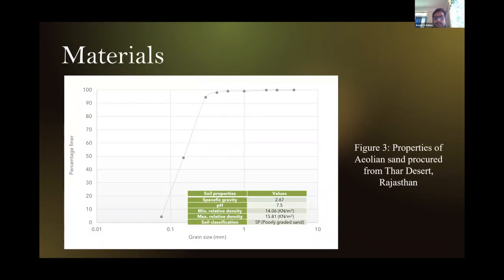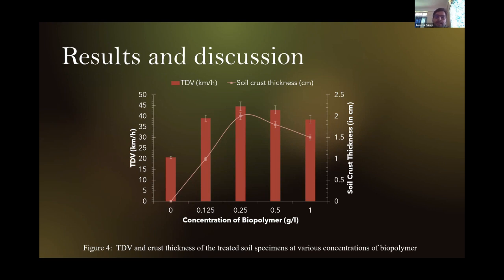So we collected the soil from Thar Desert, Rajasthan, specifically from Jaisalmer district. And these are the properties. It is a poorly graded sand with less than 5% fine content in it. And the results showed that the threshold detachment velocity for the untreated sand, shown here by zero, was around 20 kmph. And when we introduced only 0.125 gram per liter of xanthan gum, it improved by more than 90%. It is to be noted that in these areas there is another common practice of mixing sugar with water, but that is not found suitable for erosion mitigation.